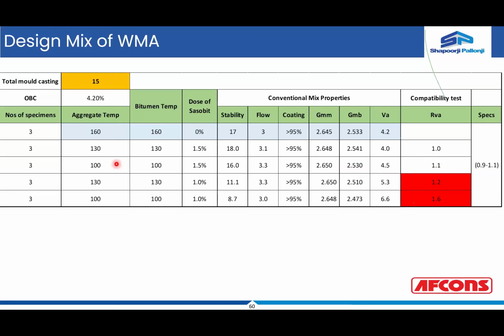So if you see, for all practical purposes, the hot mix which you are supposed to use is 130, 130, thus row 2, wherein your value is 1. So if you are reducing the Sasobit dose from say 1.5 to 1%, you can see that your compatibility test indicated values of 1.2 and 1.6, which is not meeting the requirement of the specification that your air void ratio should be in the range of 0.9 to 1.1. So your controlling factor is the air void ratio when you are converting your hot mix into a warm mix as well.